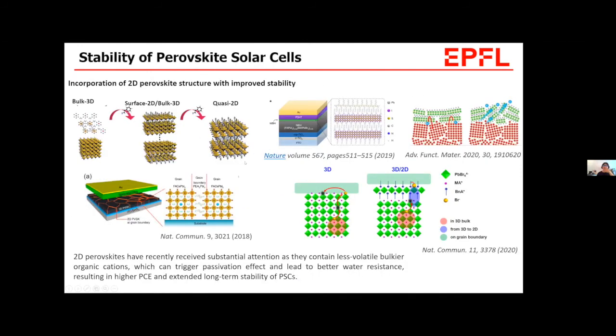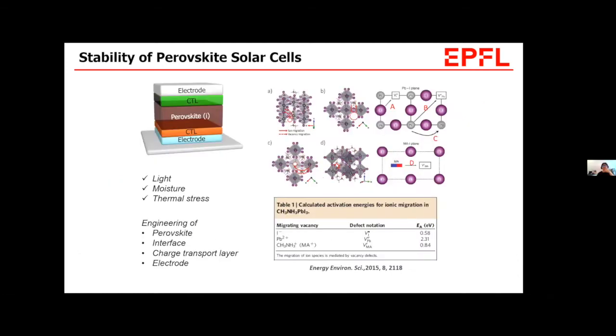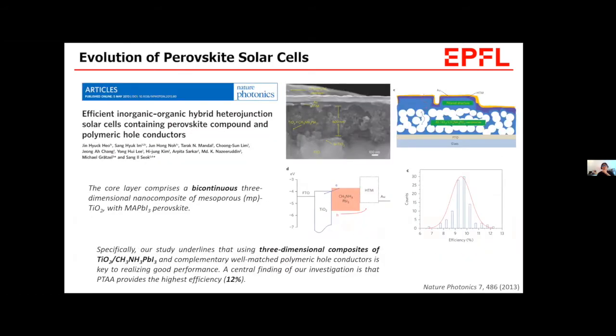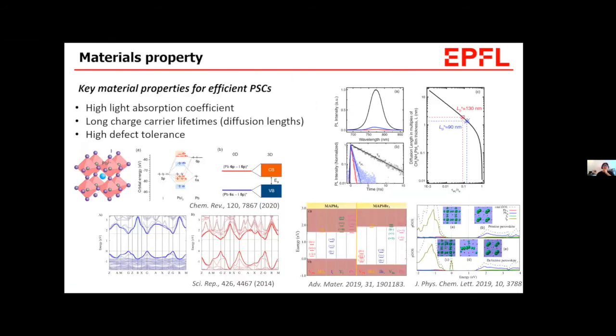So the main reason of this high defect tolerance of perovskite is, as far as I know, I have to look through it again, but this is because of the strong spin orbit coupling of lead, this heavy atom inside.